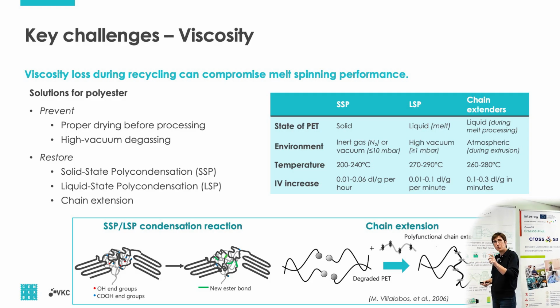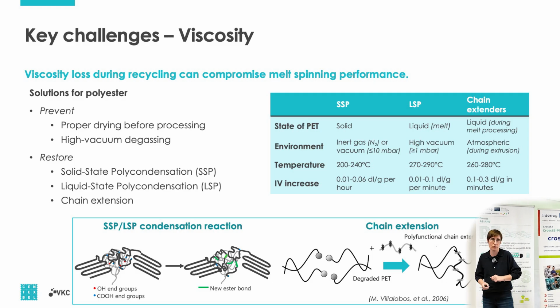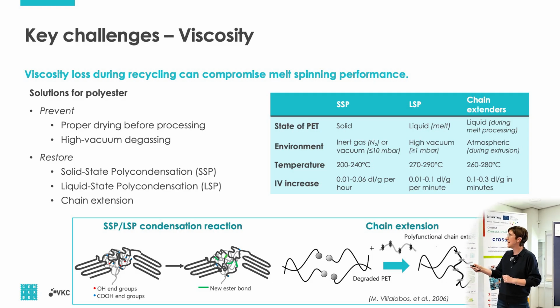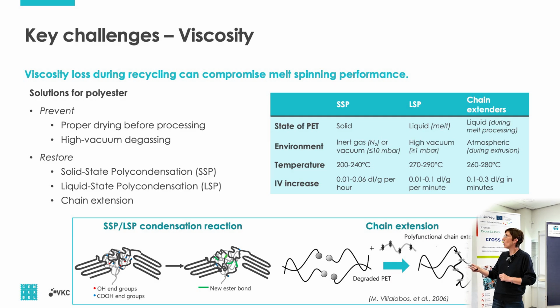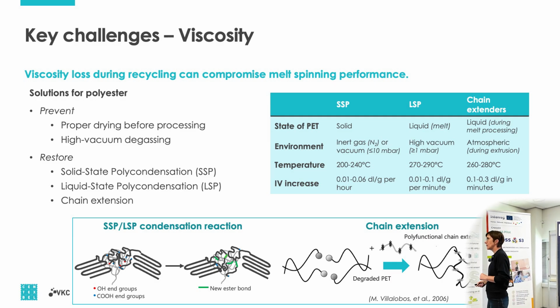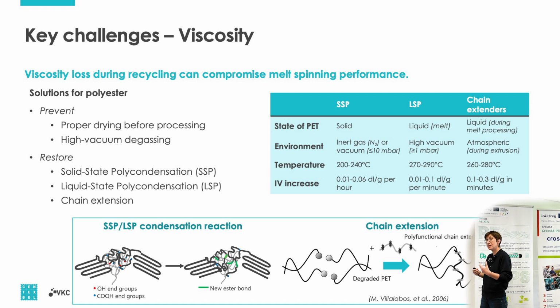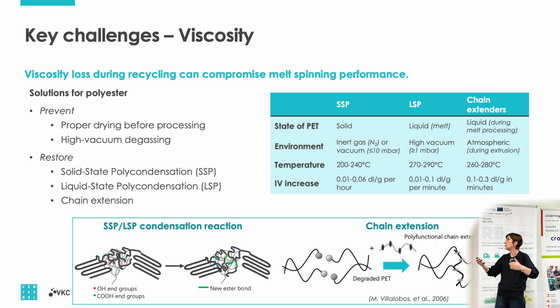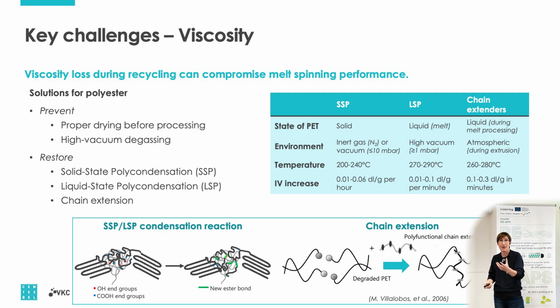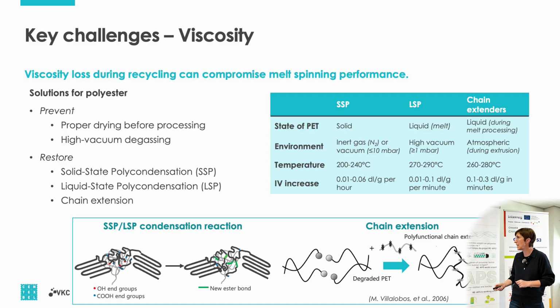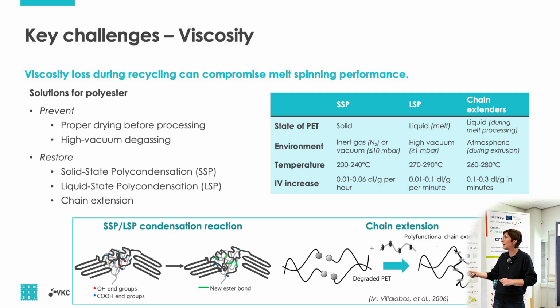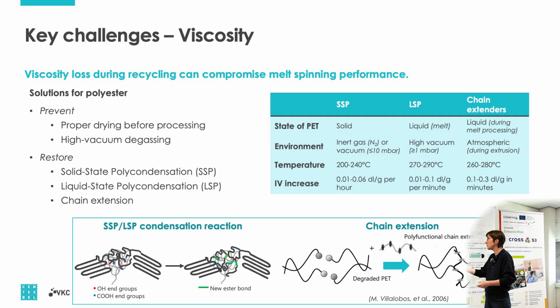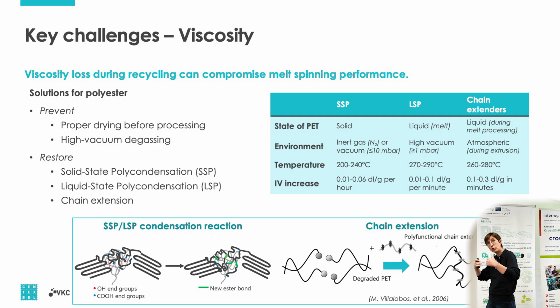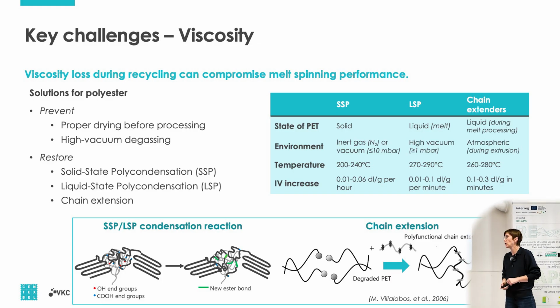That's the reason a lot of machine constructors are looking at those other two technologies. And what are the other two? SSP and LSP, so solid state or liquid state polycondensation. What we try to do there is increase the IV after our processing. Liquid state means in the melt. Solid state means we have our pellets and reprocess them in SSP equipment, at high pressure and high temperature. But you see here, it takes some time. Typically 24 hours, a batch reaction step, while the LSP takes minutes and can be coupled after your extruder, in line with your extruder technology.